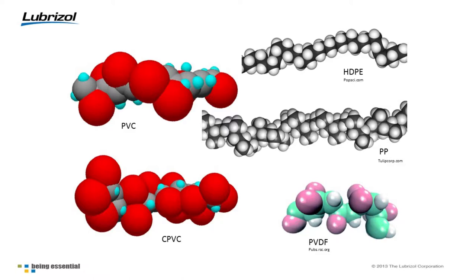Twenty parts per million of hypochlorite in a caustic stream can totally kill polypropylene, because sodium hypochlorite is a strong oxidizer. These types of polymers require the presence of an antioxidant to protect them from oxidizers like bleach or sulfuric acid. The antioxidant is sacrificial, so it does go away over time. Eventually it will be depleted and the oxidizer will destroy the HDPE or polypropylene.